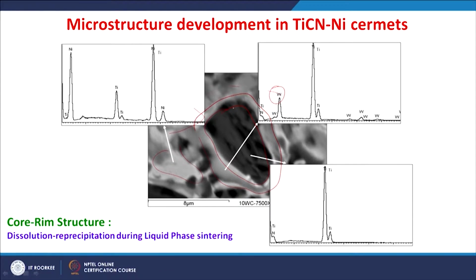So, the core and rim structure is believed to develop by liquid phase sintering. When the liquid forms, like nickel having a lower melting point than titanium carbonitride, while sintering these cermets, this nickel melt will penetrate among the particles of these ceramics, titanium carbonitride and the respective carbides.